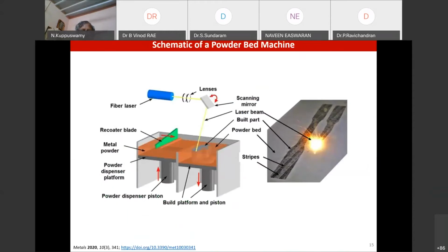Okay, now let's come back to powder bed. This is how the schematic of a typical powder bed machine looks. You have one hopper, which is where the powder is fed, and normally the powder feeding hopper will keep going upward to keep on feeding powder. Therefore, you start with one layer of powder, and then the laser beam moves as per the G code or as per the geometry, and sinters only the profile that has to be sintered in the powder. Now, for the next layer, the build platform comes down by, let's say, 50 micron, and then the powder hopper goes up, and then the blade spreads the powder around, and the excess powder gets pushed off into one end. And then the process repeats. The laser is scanned as per the geometry, and the sintering happens only as per the geometry, and then the unused powder is pushed out, and the whole process starts again.